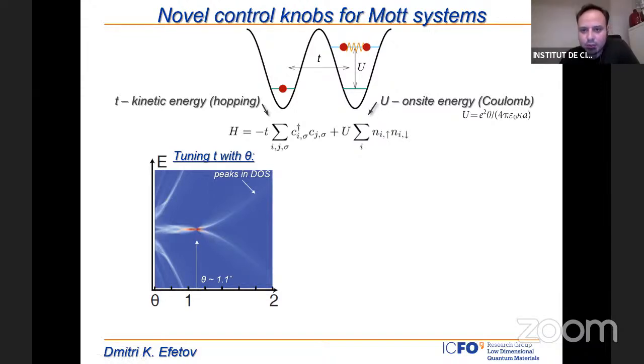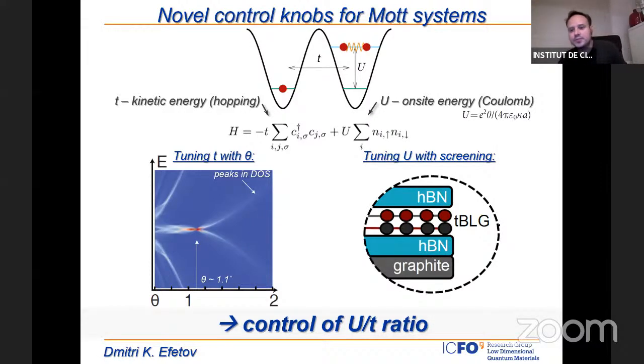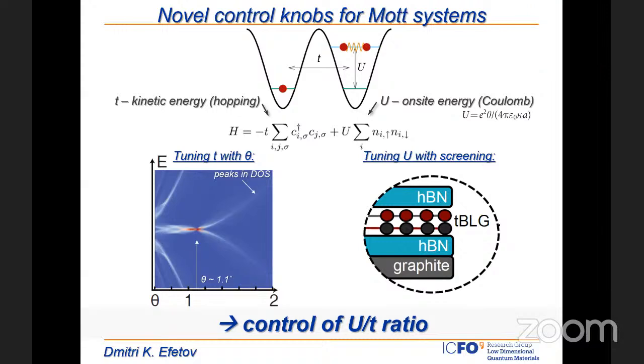Then the other thing is that U is also tunable. If you look at the cross section here, we have a really complicated dielectric environment. We have these insulators, hBN, and we have this metallic graphite, which is very close to it. This allows us to change the dielectric environment and even introduce screening layers to the twisted bilayer graphene, and therefore we can change U. So bottom line, it appears possible to change this U versus T ratio and then see what happens to the correlated insulators.